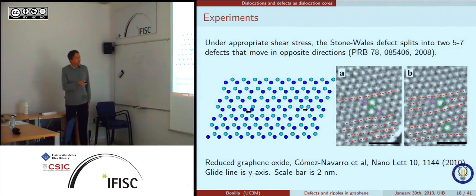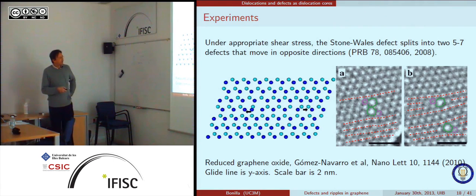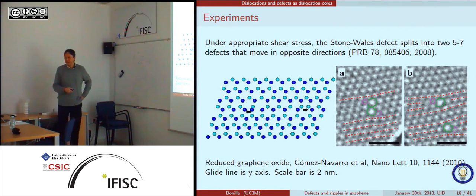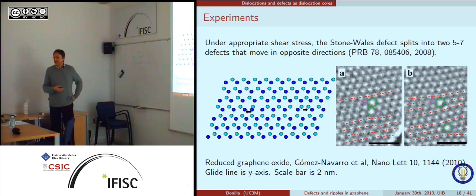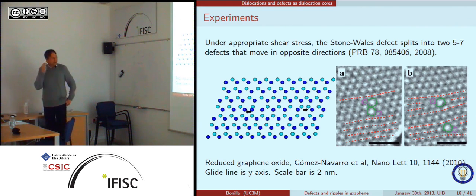This is some experiment that was done later on with reduced graphene oxide, where you start from graphene oxide and then reduce it. You take away the oxygen, and that thing is known to produce a lot of residual stress inside the sample. It gets a lot of defects and residual stress. So here you create a Stone-Wales defect inside a region where there is a huge strain. And so what happens is that if you wait a little bit, the two defects come apart as in the simulation I showed, but of course by natural process.